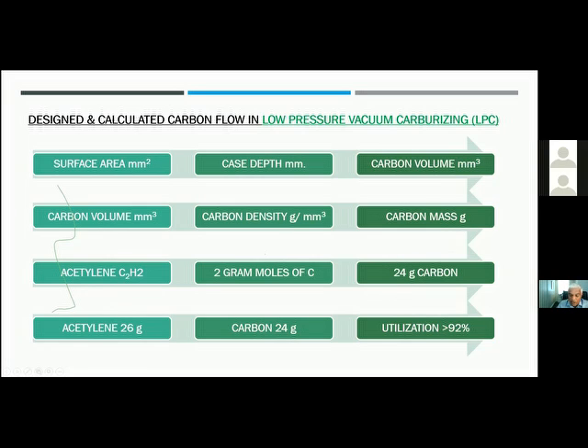in the system. So you actually have 24 grams of carbon if you introduce 26 grams of acetylene. So you know the carbon mass you need to bring into the system. If you divide it by 24 and multiply it by 26, you will know the mass of acetylene you need to bring in. And that is transferred into a mass flow transducer. And this is transferred not in one lot, but it's transferred with certain amplitude, certain frequency, over a certain incline. So you can grade all this very well. But that is the design calculation of the carbon into the system.